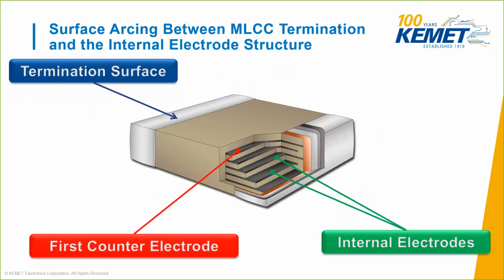In the previous slide, we showed how arcing can occur between the two terminations of the MLCCs. This slide shows that the arcing can occur between the termination and the actual internal electrode structure. When this happens, instead of arcing across the surface of the MLCC, it travels from the termination of the MLCC to the first opposing electrode, causing a dielectric breakdown.